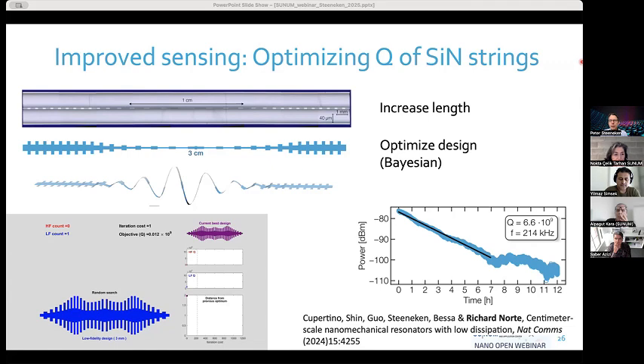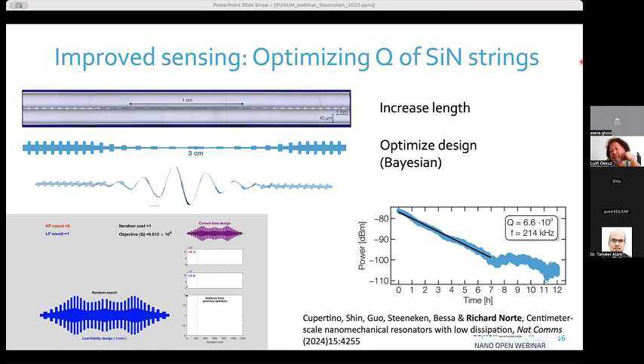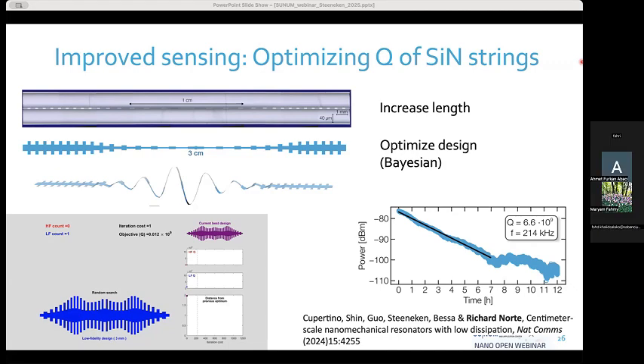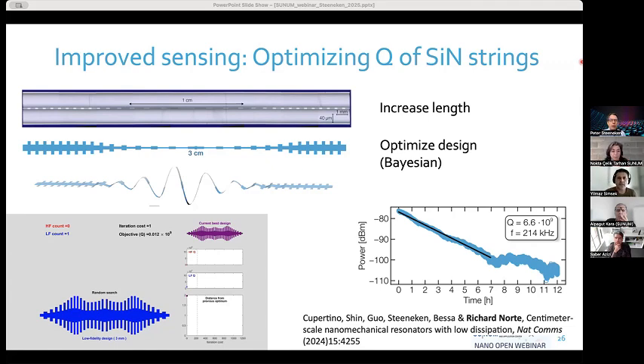So we did not use Raman. Raman can be used to measure strains. However, the resolution of Raman for strain is not as high as the resonance frequency. So we did not do it in this case. The strains that we are seeing, or the change in the strains, are probably too small to detect via Raman, although it depends a little bit on how good your Raman system is, of course. The increased sound speed during higher tension was purely an effect of the mechanical properties. There were no strain-induced transitions occurring. Although those can occur at high strains, in this case, I don't think this was happening. The strains are too low to cause those transitions. But thanks for the question.